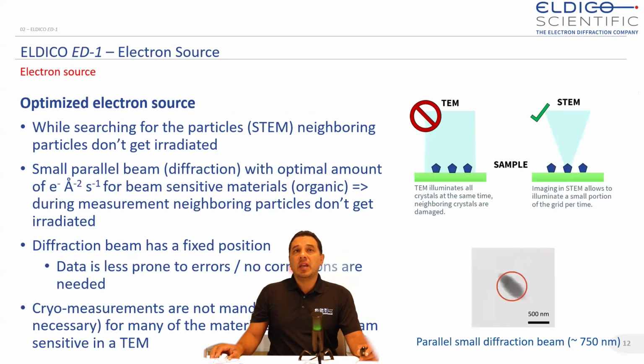So what other features do we have in this device compared to a microscope? Well, while searching for particles, most of the time in a microscope you would be using TEM mode. We use the STEM mode. What does that mean? In TEM mode you're illuminating all your particles before you have even started your electron diffraction experiment, and therefore particles which are beam sensitive would just die faster in your experiment. So we have a very small beam, and the flux density is also optimized so that we can even treat organic materials at room temperature.